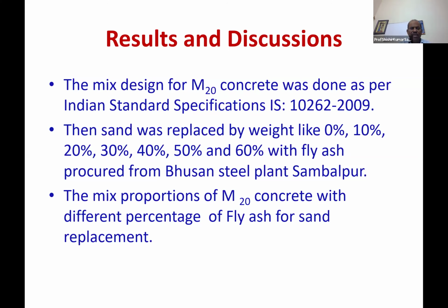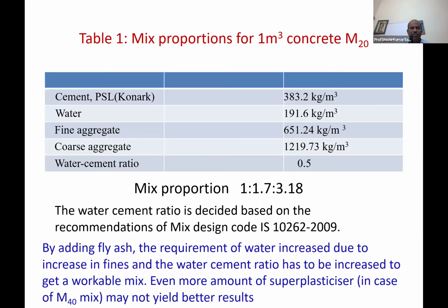Different percentages of fly ash. This is the mix proportion. This is slag cement of this proportion we have used. 1:1.7 to 3.18. The water cement ratio is decided based on the recommendation of the mix design code. By adding fly ash, the requirement of water increased due to increase in fines, and the water cement ratio has to be increased to get a workable mix.